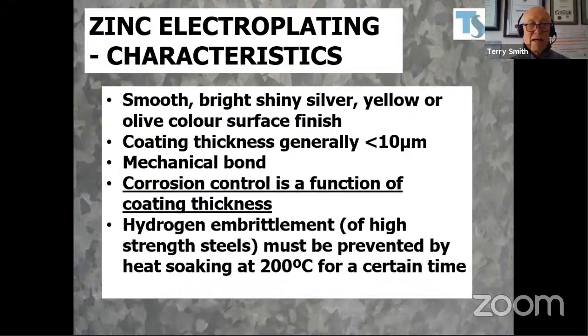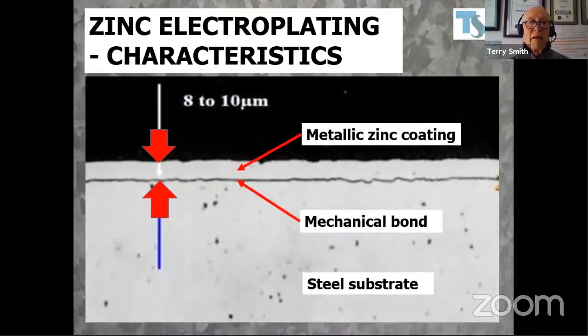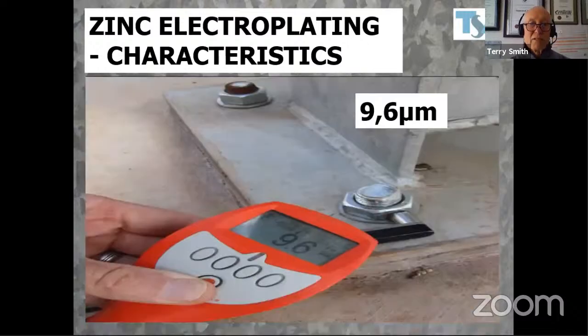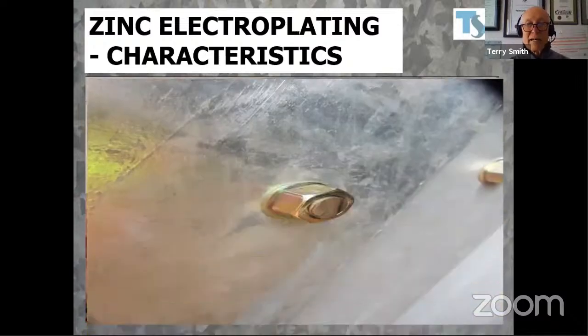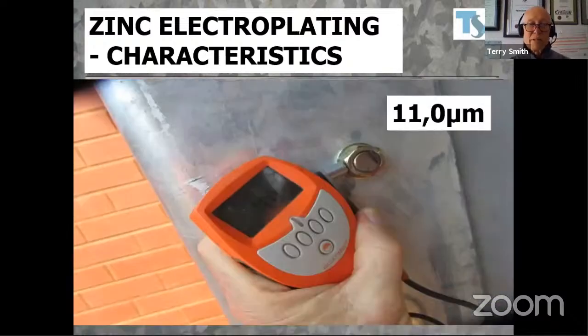Hydrogen embrittlement of high strength steels must be prevented by heat soaking at about 200 degrees C for a certain time to drive off the nascent hydrogen. And you can see a typical micrograph of electroplated coating. You can see the mechanical bond. There's no iron zinc alloys there at all, around 8 to 10 microns. You can see a typical zinc electroplated bolt, which is silver in color, and here's one which is yellow. Here's a typical coating thickness of that nut.